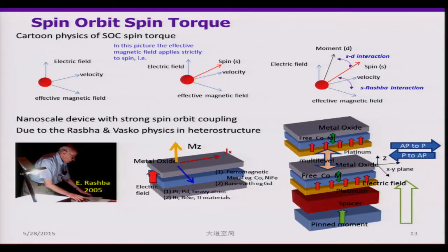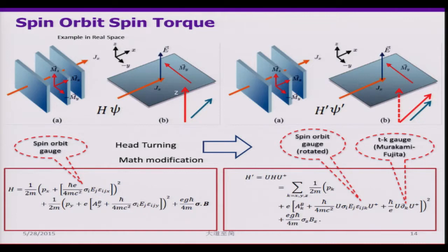How about if I have a layer with very strong Spinorbit coupling, and I use this layer to generate spin current. And at the same time, this layer also stores information in the form of magnetization, which means I can do 2 things together: first, convert a charge current into a spin current, and second, use the spin current to switch the magnetization. Therefore, people are making use of the Spinorbit coupling to switch the magnetization, and that's what we mean by Spinorbit Torque here.